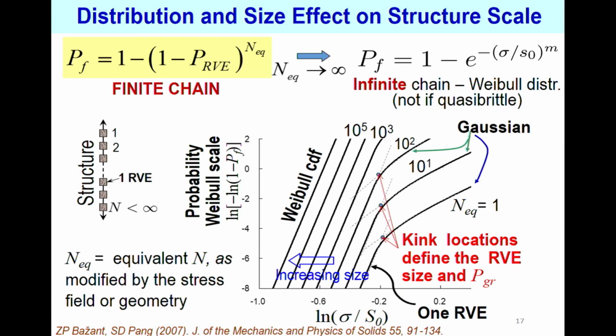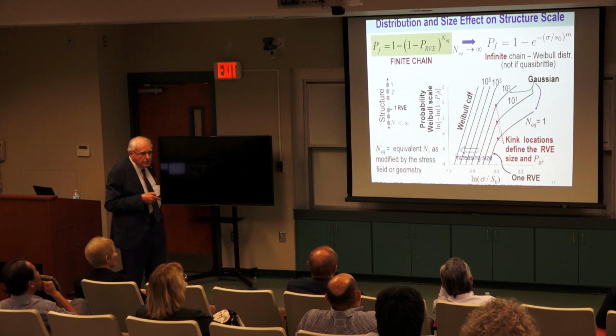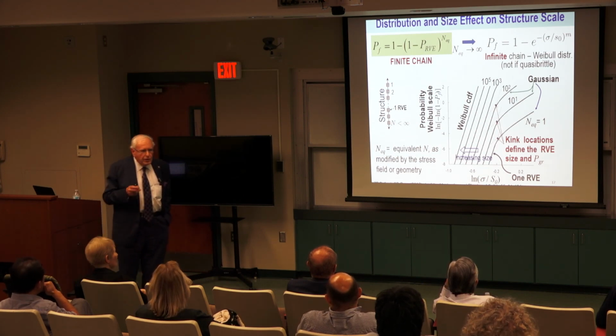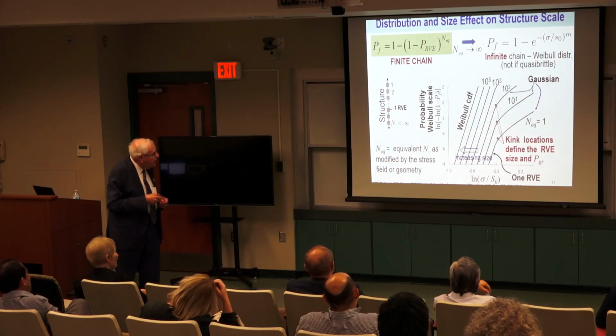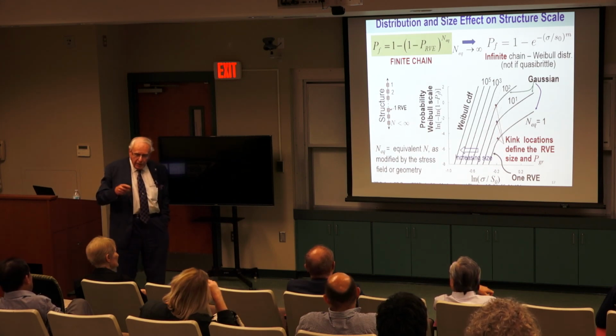Now there is another interesting point. This Weibull distribution, which is shown here, is typically considered in engineering as sigma minus a constant. And the argument is intuitively, we know that for low enough stress it will never fail, right? But do we really need it? Now if the exponent is typically like in concrete 24, in some metals 30 to 50, if the exponent of this law is so large, and if the stress is 1/3 of the maximum, you will find out that for the break to occur, you would need to wait 100 times longer than the age of the Earth. Okay? So we don't need a threshold.